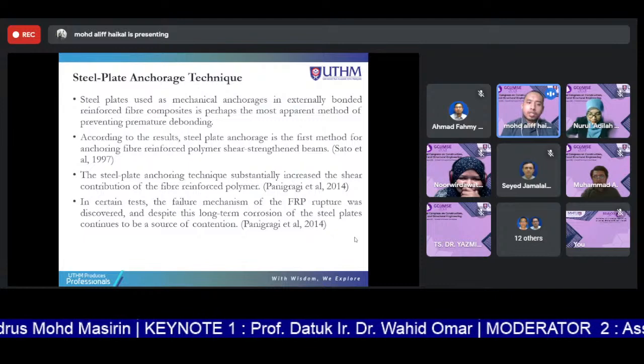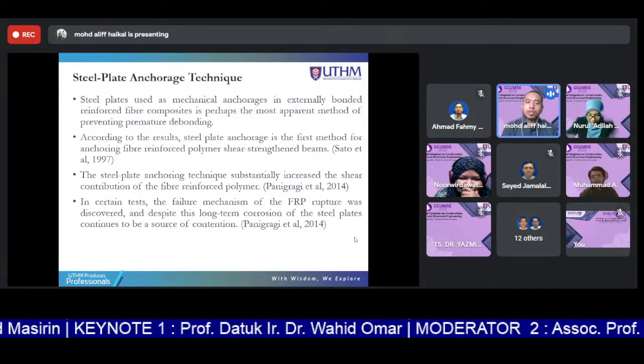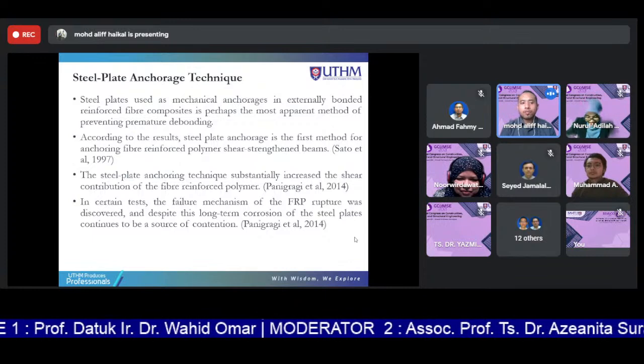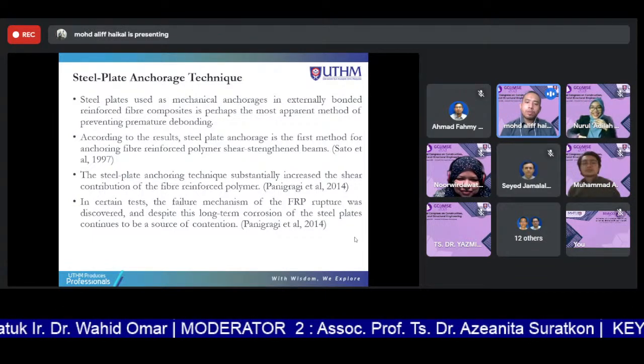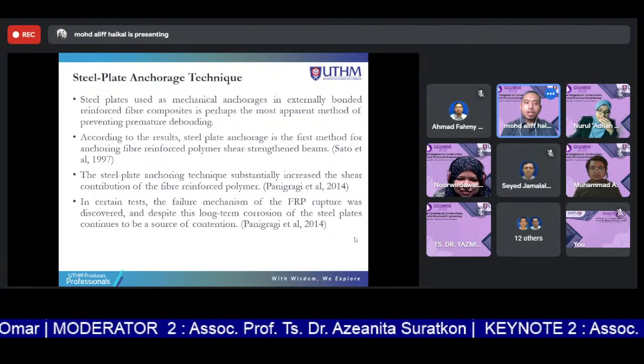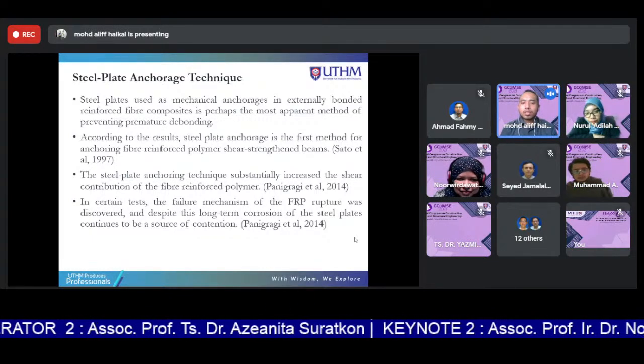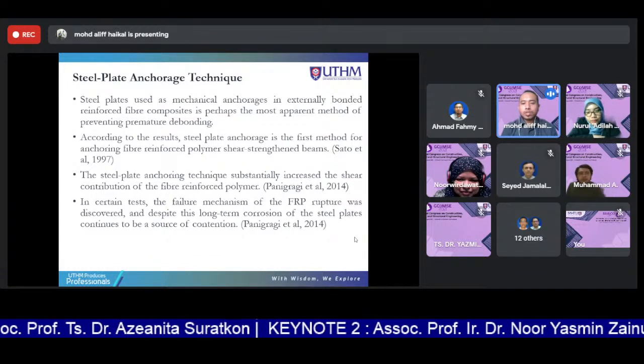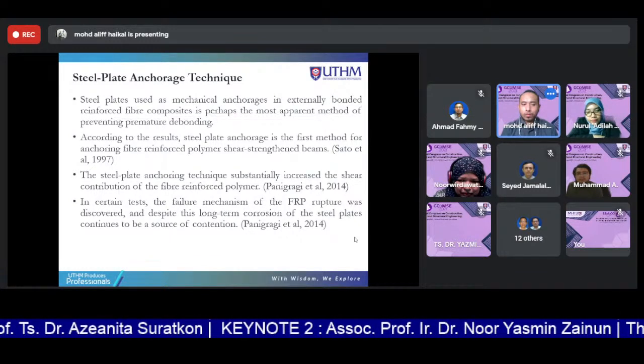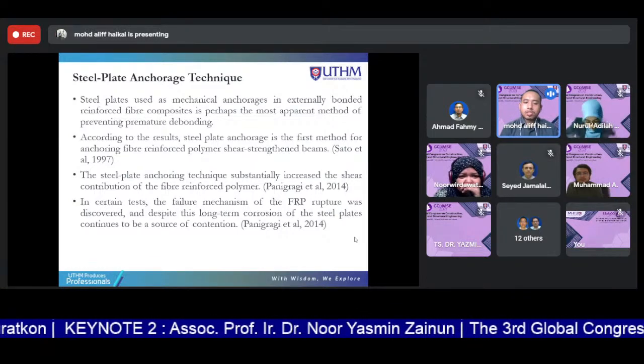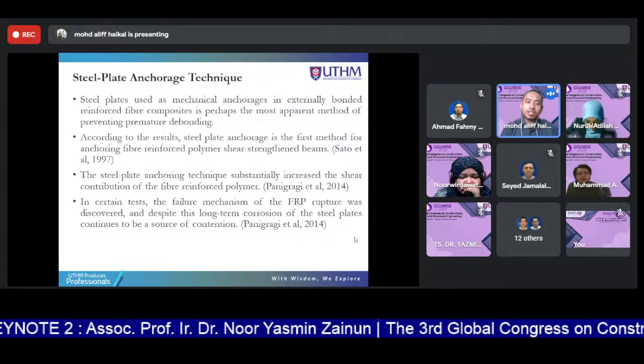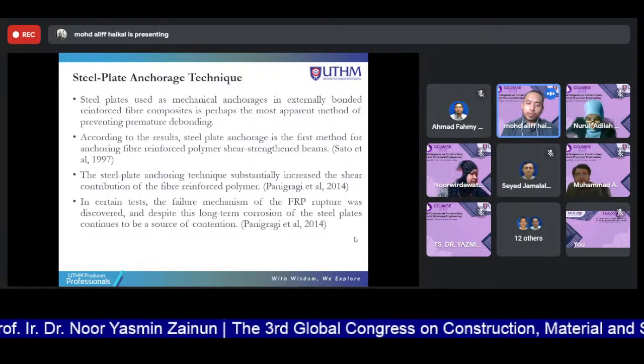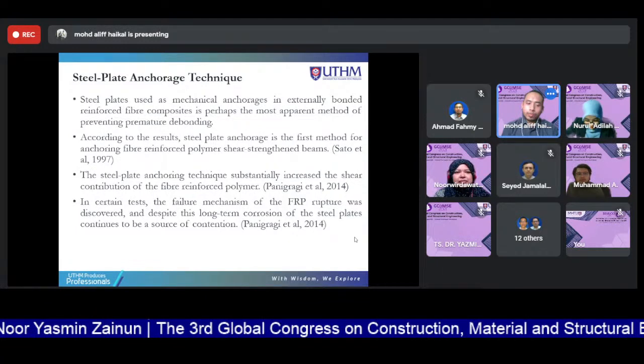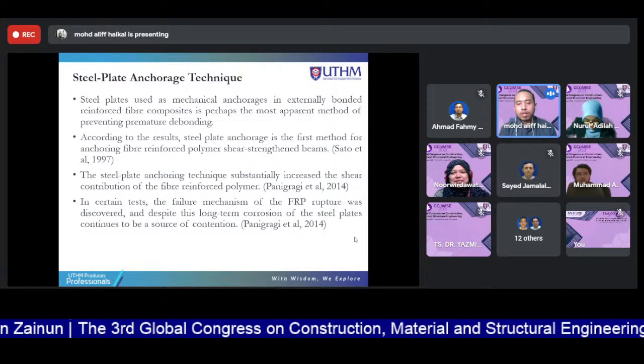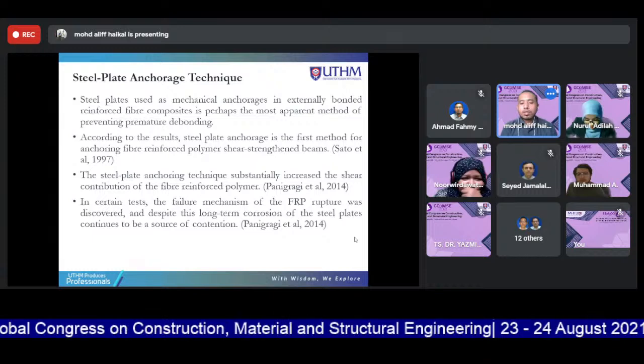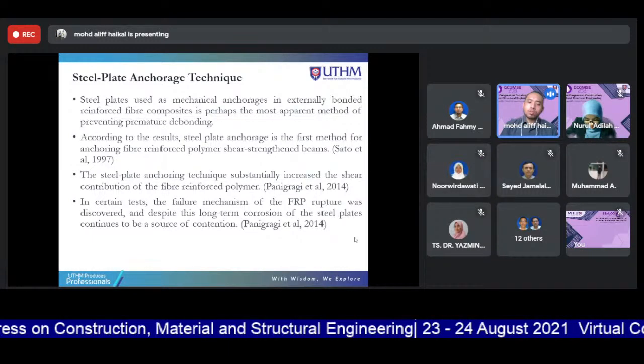For the steel plate anchorage technique, the steel plate is used as a mechanical anchorage in externally bonded fiber reinforced composite. It is perhaps the most apparent method of preventing premature debonding. According to the result, steel plate anchoring is the first method for anchoring fiber reinforced polymer shear strengthened beams, by Sato et al. Okay, the steel plate anchoring substantially increased the shear contribution of the fiber reinforced polymer, and in certain tests, the failure mechanism of FRP rupture was discovered. Despite this, long-term corrosion of the steel plate continued to be a source of contention.